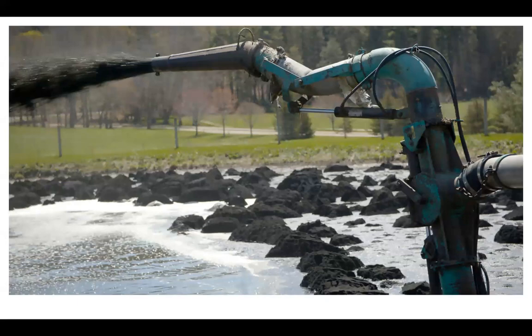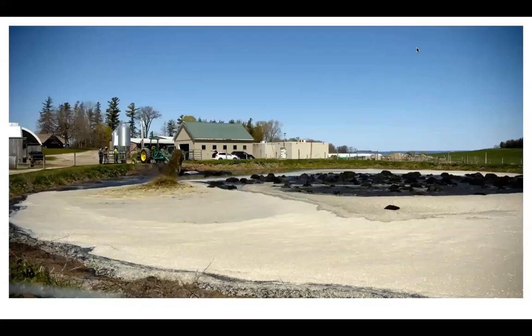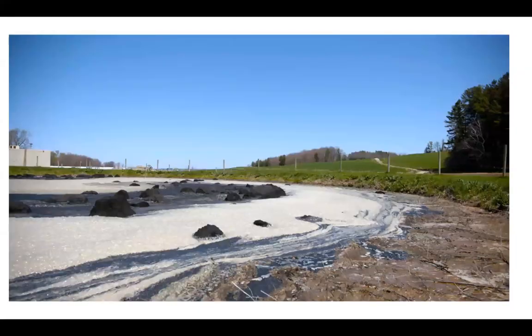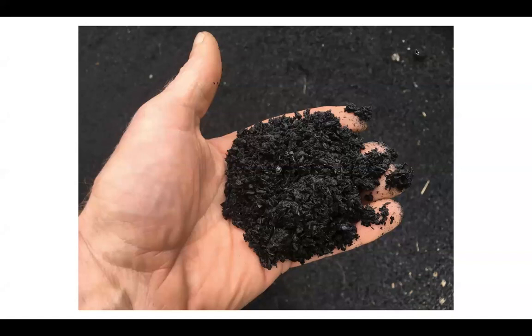And you can go to the next slide. And this is it mixing in as we had to agitate the biochar to spread it out and mix it in across the surface. And go to the next slide. This is just it mixing in that same day. When we did this in May at the beginning of the season, because my understanding was most of the nitrous oxide emissions come from your manure pits in the summer months. Basically, when it's frozen, you don't get as many emissions. And then we can go to the next slide. And this is what the material looked like.